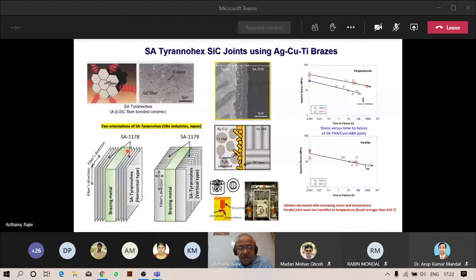But the interesting difference was that the stress rupture behavior is different for fibers bonded in different orientations. What we found was that the joints where the fibers were parallel to the brazed region, the joint was less sensitive to temperature as compared to when we had fibers perpendicular to the joint interface. And that could potentially be a reason, or it could be due to the low interlaminar shear strength of this material. And of course, we are seeing the decrease in lifetime with increasing temperature, which is what you would expect in a general case. But this was an interesting new thing we found. The orientation of the fibers at the joint region will affect the rupture behavior.